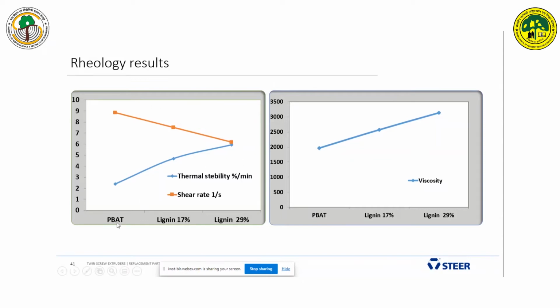Here the PBAT was here, and when you compare the thermal stability and also the shear rate, with the addition of lignin, the thermal stability of the PBAT was improved. That shows the lignin had better thermal stability, and the shear rate was reduced with the addition of lignin, which is also a good thing. With the virgin PBAT the thermal stability is here and also the shear rate here, but with the addition of lignin there is improved thermal stability and reduced shear rate. That gives the indication that the lignin was lubricating the polymer, even though polymer-screw friction reduces.